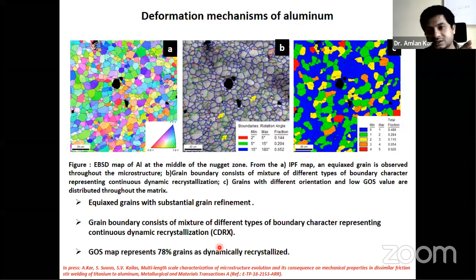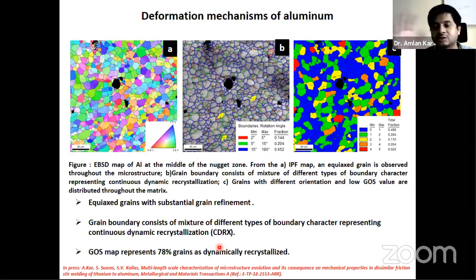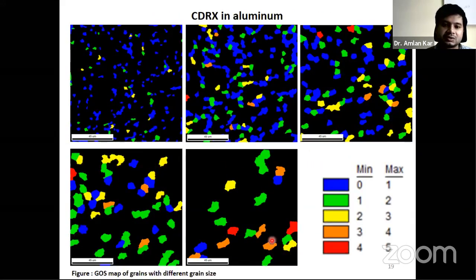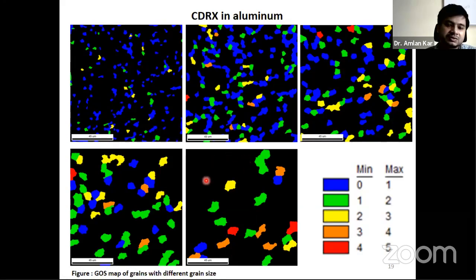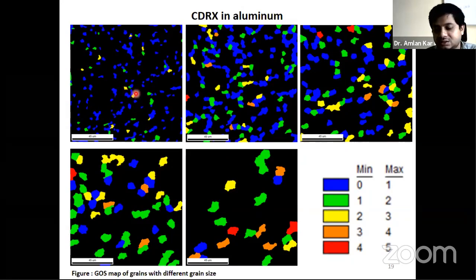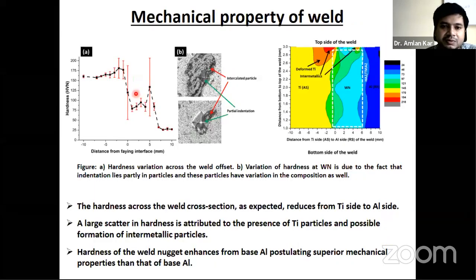So the aluminum side is totally recrystallized and it has a lower flow stress, but on the titanium side we have a strong material like titanium which has not been recrystallized, which is subjected to low temperature deformation. So this is clear evidence of that, and from this microstructure we can also see the GOS map with different grain size. We can see the bigger grains are subjected to deformation. This is not a low value of GOS, but in the very fine grains, we can see a very low value of GOS. So that represents, in the case of aluminum, that the bigger grain is subjected to deformation leading to the finer grain. It is a process of grain refinement in the case of aluminum.